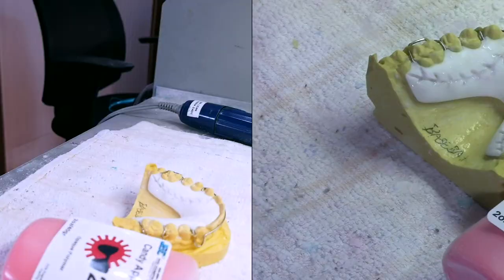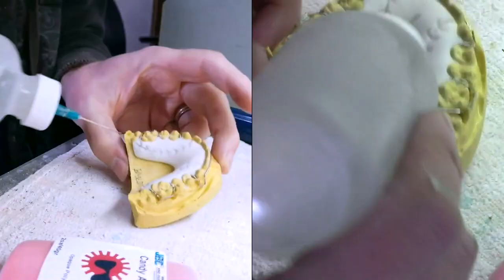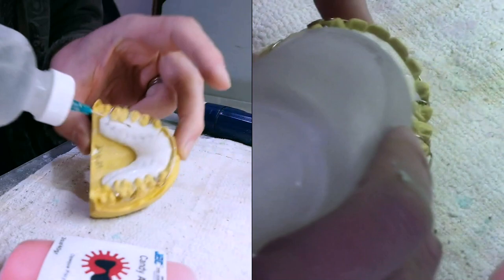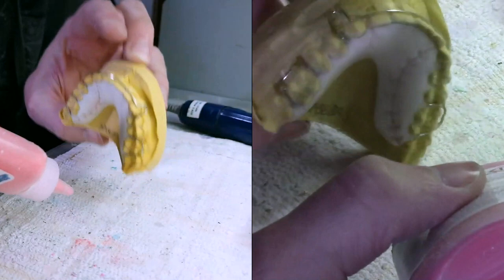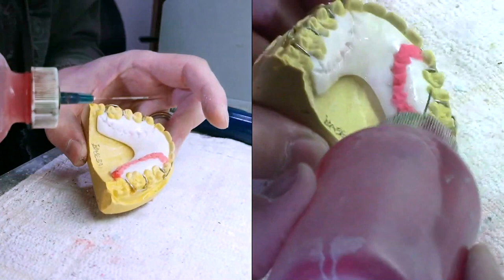Red stitches time. I like to use Candy Apple Red Polymer from JBC — I think it gives a good, nice, rich red color with good contrast for the white. But first things first, I'm going to use clear monomer and spray it into the inlay trenches that I just ground out. That way, when I sprinkle the polymer in, it will reduce the risk of air bubbles and polymer pockets in the retainer. There will be a chance that if you put polymer down and then put monomer on top, you'll have a problem getting acrylic into all the nooks and crannies you just ground in there.